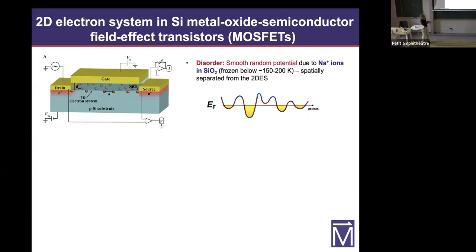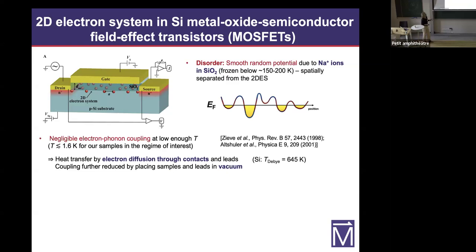And the origin of this disorder are the positively charged sodium ions that are randomly distributed throughout the oxide, and they're frozen at low temperatures. They're spatially separated from the 2D layer. So what the electrons feel is this smooth random potential. So we have this disorder. Now the important point for MBL is something that has been known for a long time, that electron-phonon coupling in the silicon is very weak, including coupling between the 2D layer and phonons in the silicon.